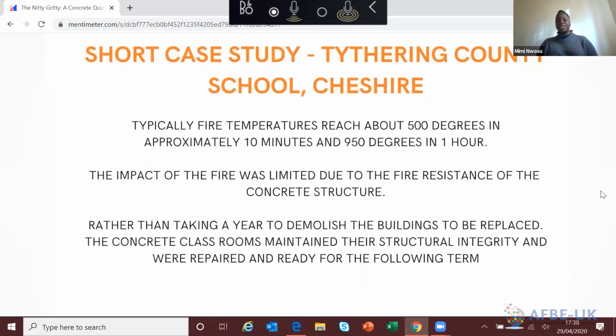Whilst I was doing my dissertation, I did a short study on a school in Cheshire. Typically, a fire can reach about 500 degrees in 10 minutes and 950 degrees in 1 hour. This school in Cheshire, the whole department was set on fire. This was 18 classrooms. However, the impact of this fire was very limited because of the fire resistance of the concrete structure. Essentially, the structural integrity of the building was still there. It was only the furniture, maybe the paint, and the plasterboard inside that was damaged. When I was reading the article, one of the teachers was saying that they were afraid that they'll have to postpone teaching until next year.